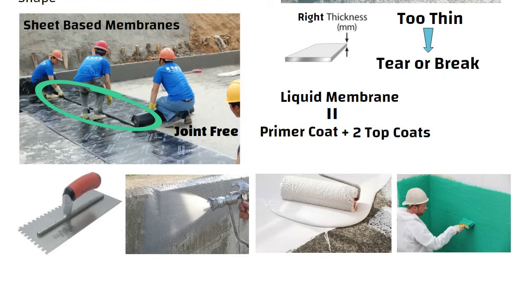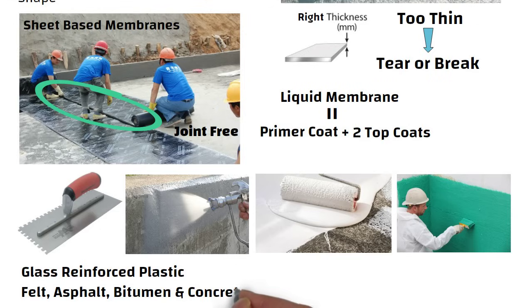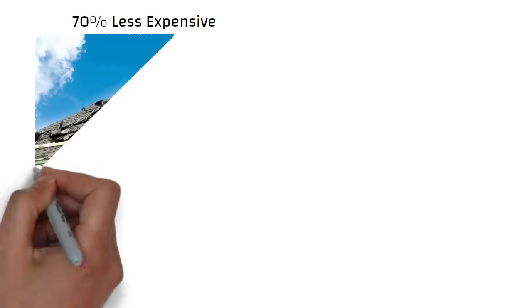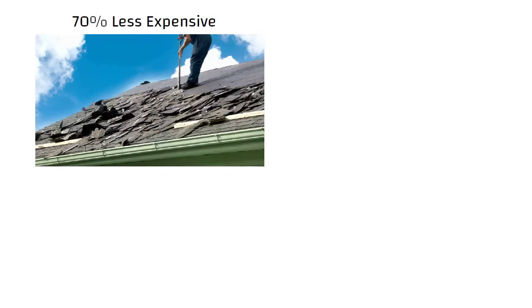Such coating systems are usually reinforced with secondary materials such as glass reinforced plastic to provide additional tensile strength. This type of waterproofing can be applied over other waterproofing materials like felt, asphalt, bitumen and concrete. It can deliver up to 25 years performance depending on the coating system employed. It is estimated that liquid waterproofing is 70% less expensive than overall roof replacement in refurbishment situations.